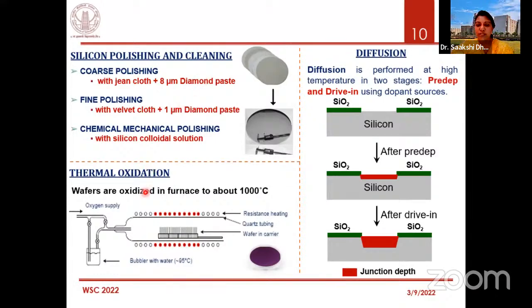And then comes thermal oxidation, which is growing silicon dioxide on a silicon wafer, right? So conventionally, silicon dioxide is known to be a material which provides very good insulation, right? Today, in terms of MOSFET, if I talk about this metal oxide, right? This oxide has now been replaced by high-K dielectric materials, which are better performing than oxide, right? So those have been replaced. But if I talk about not a transistor, right? I talk about, say, 100, 200 devices being made on a 2-inch silicon wafer, I would still require some kind of insulation between the devices, and then I do not need a high-K dielectric because I'm still not making a transistor. So thermal oxidation is one of the very basic steps we perform even when we are making MEMS-based structures.